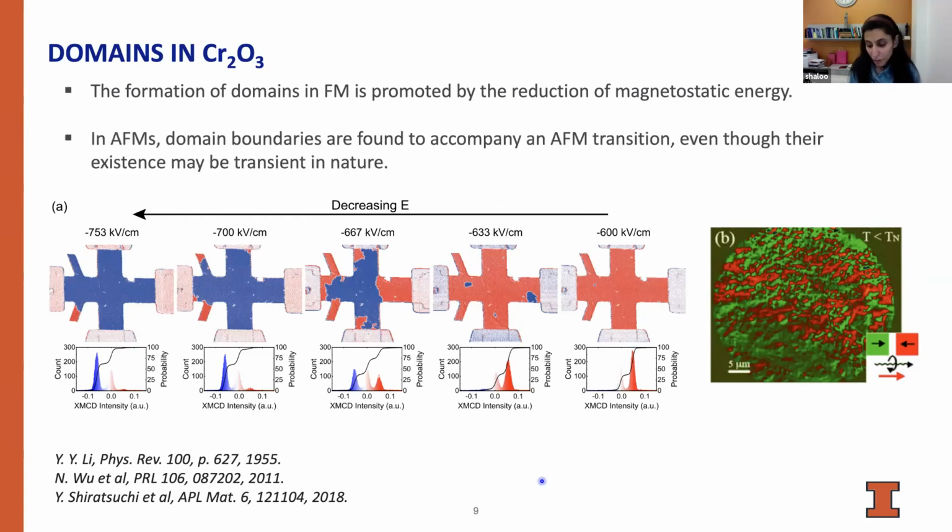And indeed, in antiferromagnets, the local nucleation of the order below the Néel temperature and its subsequent growth could lead to the formation of domain walls if the wall energy is offset by the gain in entropy. And importantly, if your sample contains defects, the domain walls could be pinned down by those defects, and then they would continue to owe their stability to the presence of these imperfections in the sample.